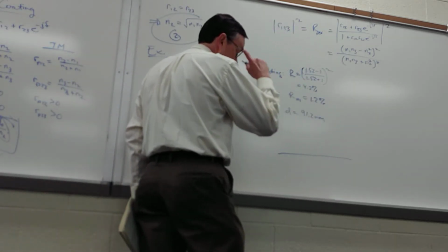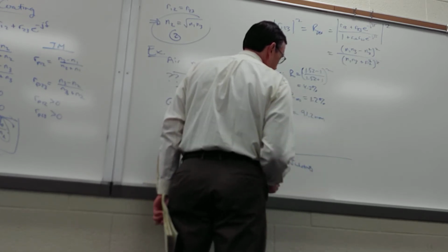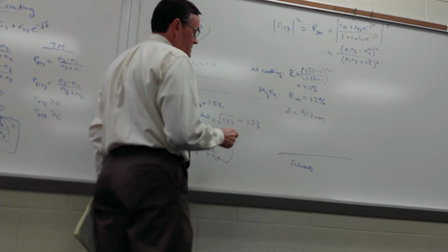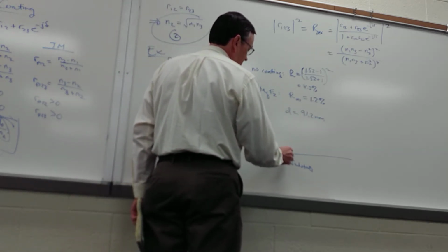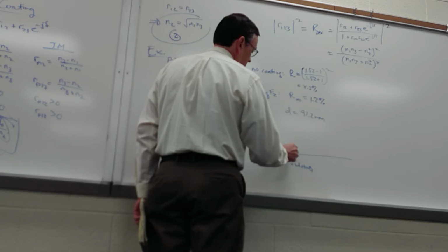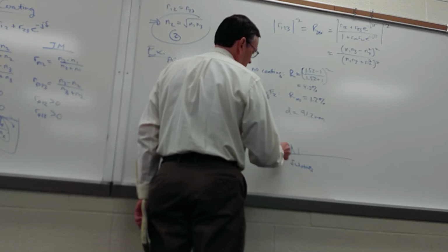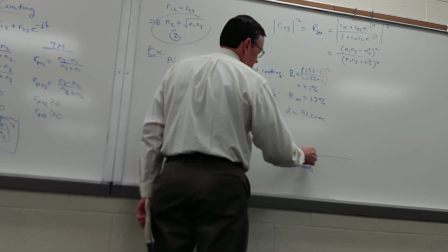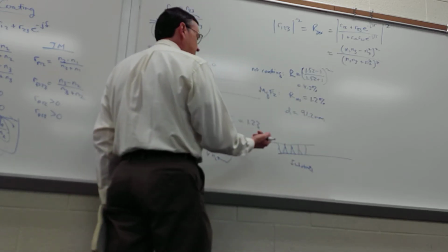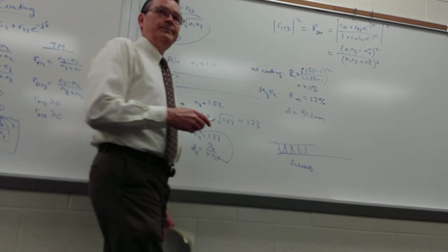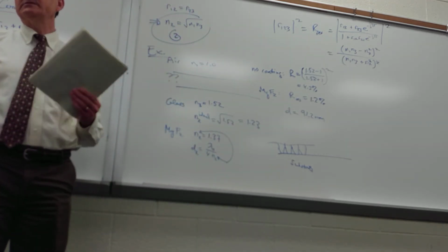then what happens is, if this is your substrate and you're depositing mag fluoride or something else, usually you get kind of columnar growth like this, and those columns spread out and then they merge, but it's still this column-like morphology. And bottom line is you get these voids in the film. And so those voids reduce the refractive index, clearly.